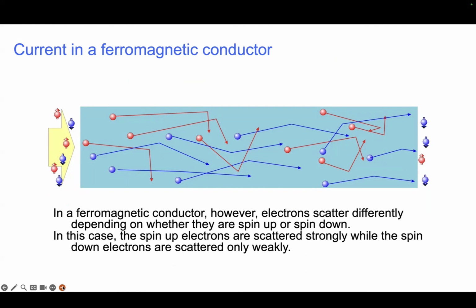So within a few mean free paths of the introduction of a spin unpolarized current from a battery, the current becomes spin polarized. And in some soft magnetic alloys like nickel iron and nickel cobalt, the current is about 70% spin polarized. This in principle leads to higher resistance in these magnetic layers.